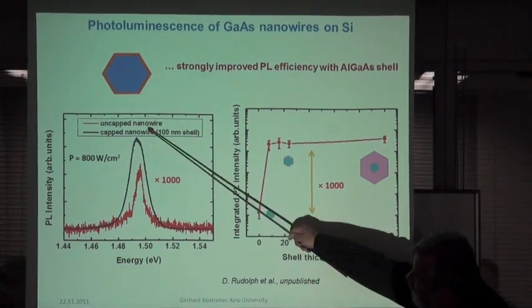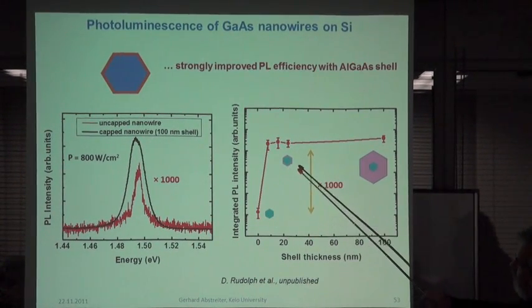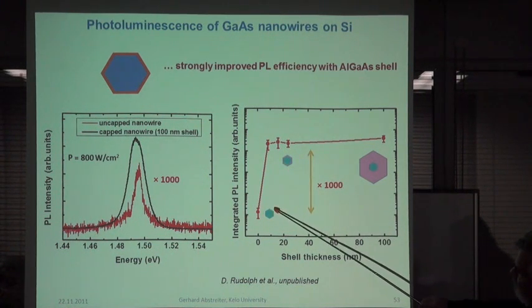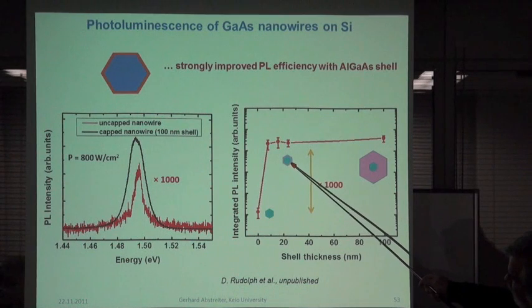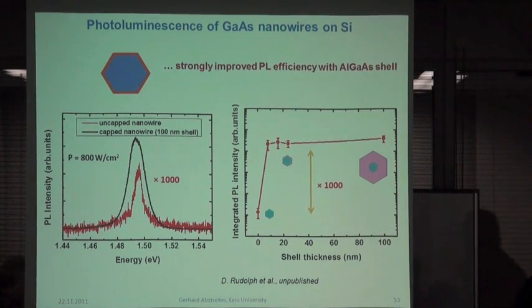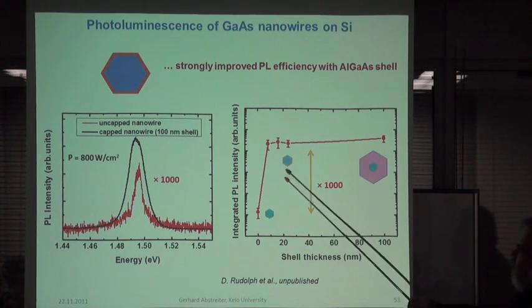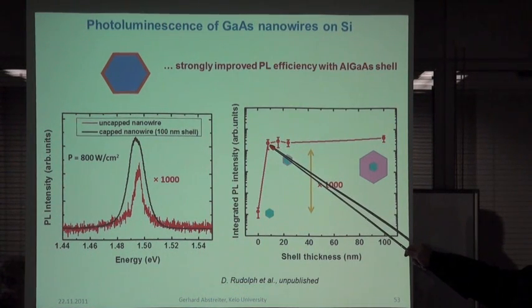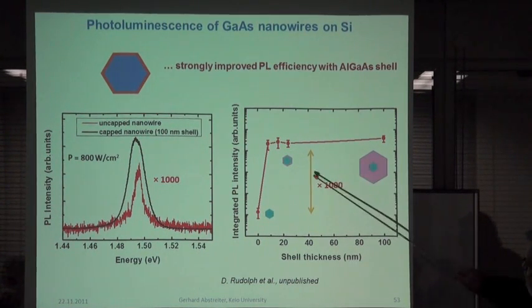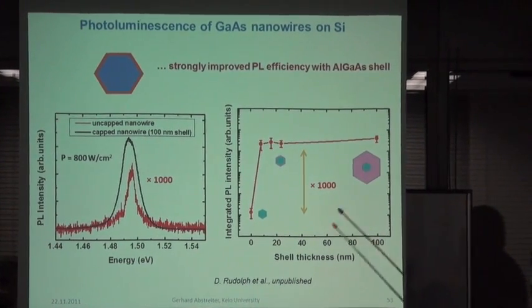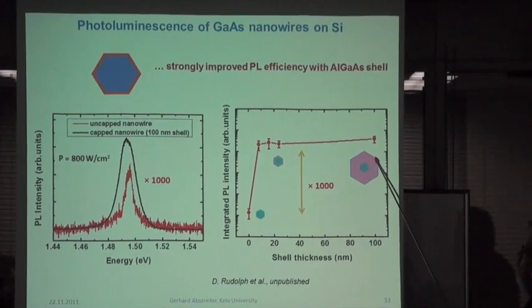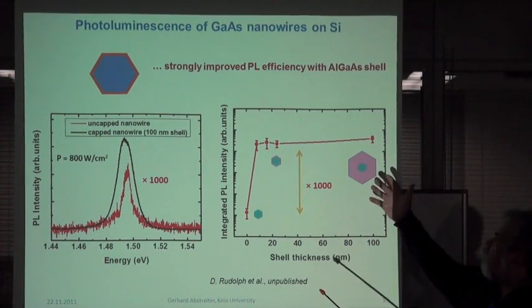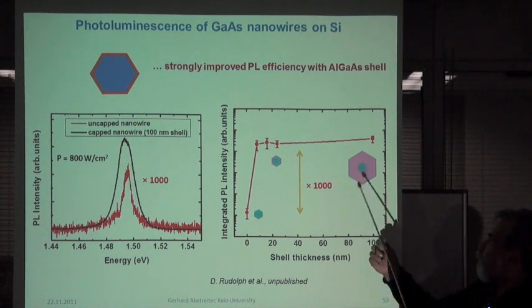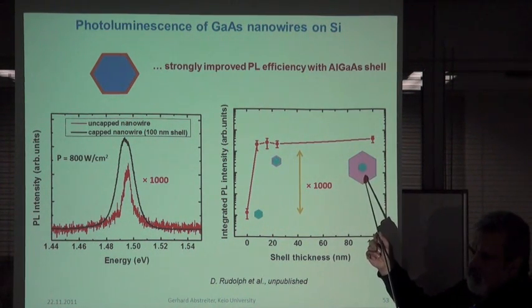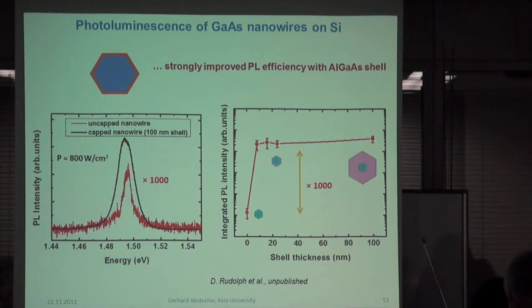We have now much cleaner wires which show a similar behavior, but the message is, if you saturate the surface states by making a heterostructure around it with aluminium gallium arsenide and a thin gallium arsenide cap, the excitons cannot have non-radiative recombination at the surface, and then you get this factor of thousands increase in intensity. It doesn't really matter, a very thin layer is already sufficient for this. Actually, this is the thickest shell, and for optics people, we can grow it thick enough that we can have wave guiding along the wire, because the core has a higher refractive index than the shell, so we get wave guiding along these wires.